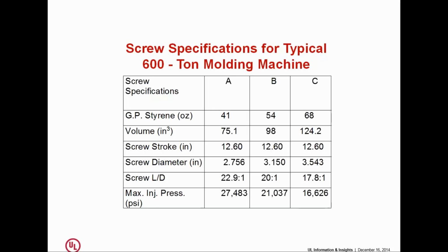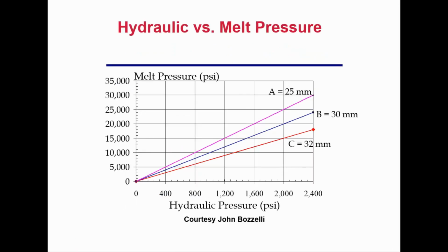Now, why is this important to us? Another way of looking at this, by the way, if you look at some of your machines, many of your machines will have this little plate that looks a lot like this, usually at the injection end of the machine. It might be affixed right to the barrel. It might be a little bit below the barrel. But this is another way of illustrating and understanding that these three barrels that you can buy with this particular machine bring with them a different relationship between the hydraulic pressure and the melt pressure that is actually generated on the plastic. So here you have a 25-millimeter barrel, which is the smallest barrel you could buy, and a 2,000 psi hydraulic pressure translates to a 25,000 psi melt pressure. So that's about a 12.5 to 1 intensifier. The next size barrel up, that same 2,000 psi hydraulic pressure only gives you 20,000 psi of melt pressure, and the largest of the barrels only gives you 15,000.